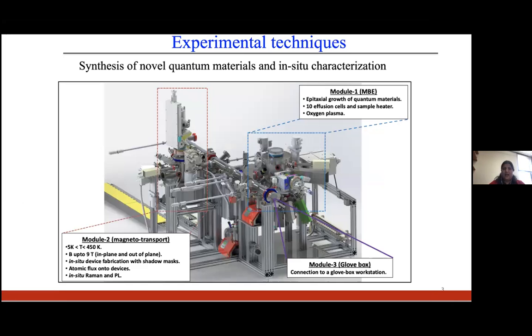And so to accomplish this goal, we are building a system where we can do material synthesis using molecular beam epitaxy, and then we can transfer a sample using this sample transfer highway and take it to this in-situ characterization chamber where we can do magneto-transport measurements. So we have capabilities like magnetic field up to 9 Tesla, and we can apply both in-plane and out-of-plane magnetic field.